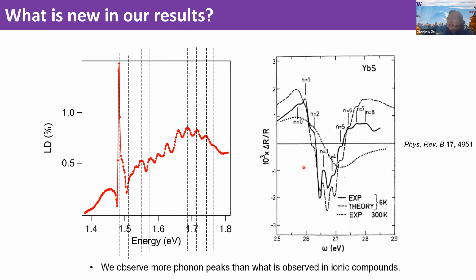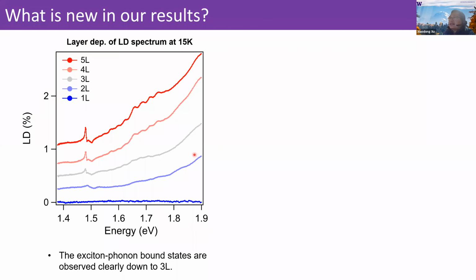And like I say, we're not the first ones to observe these. It's been done before in different crystals. But there are several new features here. The first one is what we see in many different modes, which reflects a very strong spin lattice coupling effect. And the second is that we can observe these exciton phonon bound states all the way down to a trilayer. In a bilayer, we don't see, I mean, if you use imagination, there might be something, but in the trilayer it's pretty clear, we see some wiggles. This has not been achieved before, because in the past all the exciton phonon bound states were seen in bulk